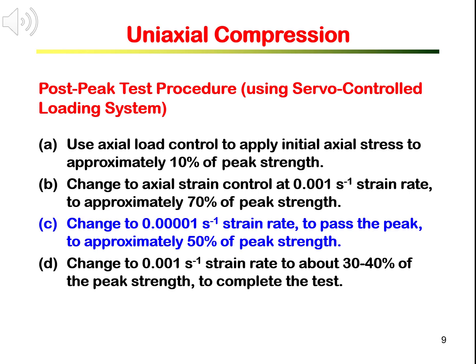The reason to apply slow axial load is to control the loading to avoid the sudden and violent failure of the rock we usually observe in normal testing. With the slow loading controlled by the axial strain rate, you will observe, in fact, the axial load decreases after passing the peak. Continue to let the axial load decrease to approximately 50% of the peak strength. Then we change the feedback axial strain rate back to 0.001 per second to increase the test speed.